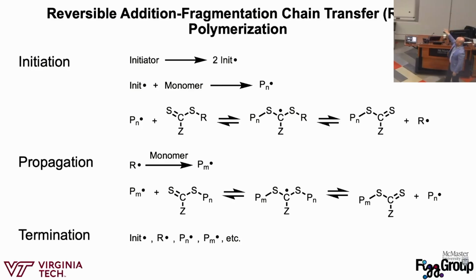But the important thing is that in the main propagation step, those radicals are thermodynamically equivalent. It's essentially the same monomers, they're thermoneutral. So we'd call this a degenerative chain transfer process, where if you're polymerizing polystyrene, this would be a polystyrene radical and this would be a polystyrene radical. And really the RAFT agent is just helping those growing polymer chains share the low concentration of radicals, so they're all growing at about the same rate. And then because this is radical chemistry, they're all going to terminate through conventional radical termination events.